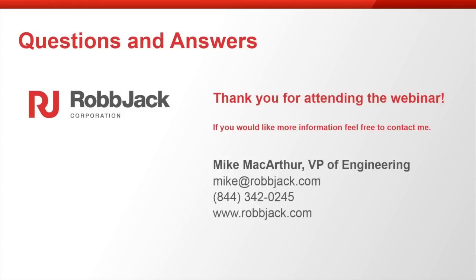Okay. All right, and we've got time for one more question here, Mike. Would you vary your cutting parameters when using PCD versus diamond-coated tooling? Yes and no. Usually the diamond-coated tooling has more flutes than the PCD typically does. Not to say that's across the board, because we have PCD cutters 1/2 inch diameter with 10 flutes available. But in general, most people that are doing heavy trimming with PCD will use 2 flutes or 3 flutes. And then when you go into the diamond coated, sometimes you'll be in 4, 6, 8 type flutes.